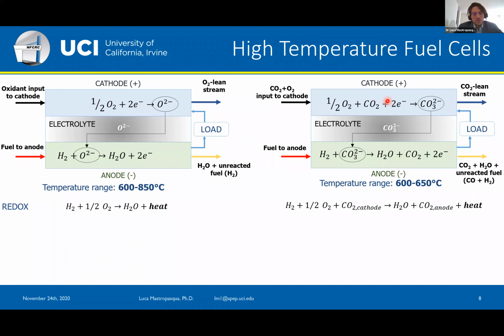Finally, for the sort of broad context, I would just like to summarize the main reactions that occur in a solid oxide fuel cell on the left-hand side and a molten carbonate fuel cell on the right-hand side. So a solid oxide cell, as I mentioned, uses a solid oxide electrolyte that conducts oxygen ions. And the oxygen ions go from the cathode to the anode, where we have the oxidation of the fuel. Operating temperature range is between 600 and 850 C. And this is why we think it's a good fit for many industrial processes.